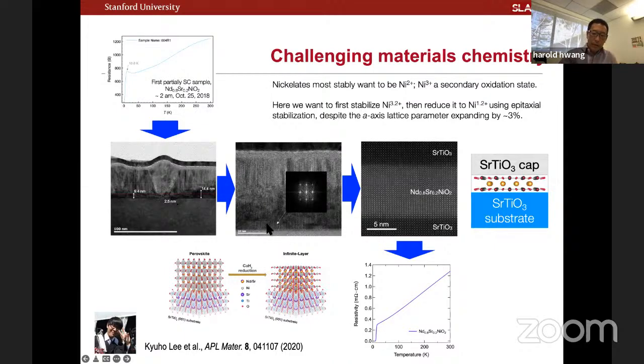So with some effort, we could expand this infinite layer phase regime. And what you can kind of imagine and see here is that the substrate gives you a director, if you will, or a proximity effect to stabilize the phase that we want. So the basic issue is that if I take the perovskite in bulk form and I want to de-intercalate planes of oxygen, I have a degeneracy, right? I can take all different cuts, and the substrate helps break that degeneracy. And so we see a proximity effect of on the order of 5, 10 nanometers or so from the substrate.